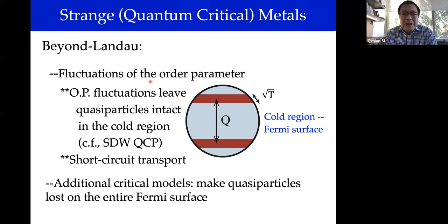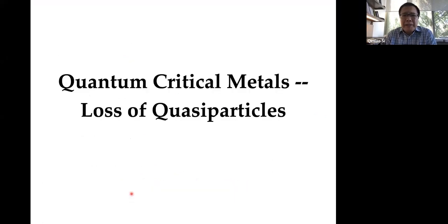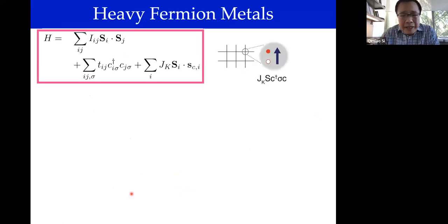So how to go beyond the order parameter fluctuations? We'll have to think about additional critical modes that have the capacity to make quasi-particles lost on the entire Fermi surface. So let me go to this particular part, heavy fermion metals, which for those which feature antiferromagnetic correlations, in the typical cases would be described by a Kondo lattice. So you can think of it as a quantum spin system and a conduction electron band, in the simplest case, that's glued together by the antiferromagnetic Kondo exchange interaction between these two species.